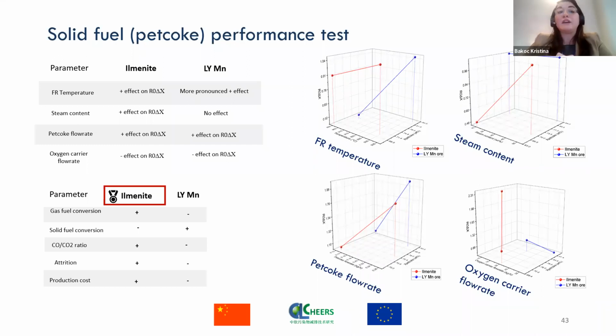And finally, if we look at the production costs and the overall pre-treatment costs, I would say for these two ores, ilmenite has lower overall pre-treatment costs than LYMN. So based on all of these parameters taken together, we would propose that ilmenite should be used as the material of choice. And in connection with the batch screening results, ilmenite T2 would probably be the best candidate based on the screening that was performed in IFPEN. So thank you very much. This is the end of our part.